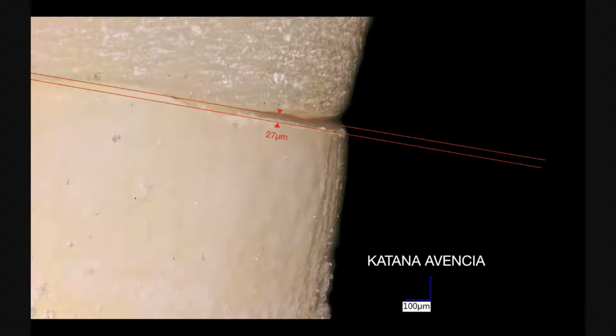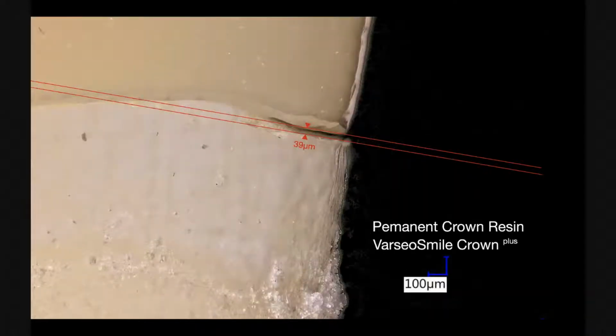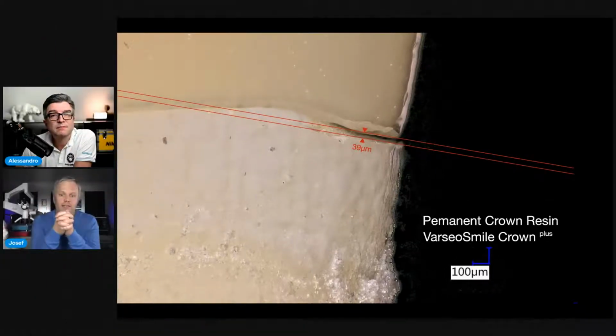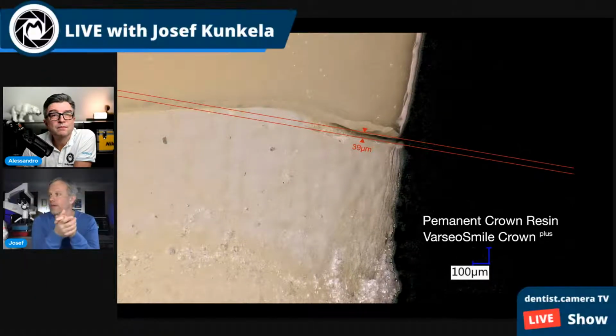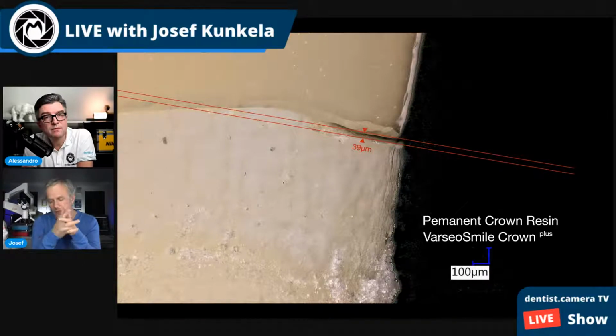And look at, for example, the composite block. The composite block is easier to mill because the material is softer and has a low elasticity modulus, there is a gap of only 27 microns. And it's very close to, for example, the permanent crown resin, where we find 39 microns, the biggest gap around 5 points of measurement around the tooth. And this is what is really amazing for me, that we can integrate 3D printing the permanent material inside our daily workflow.